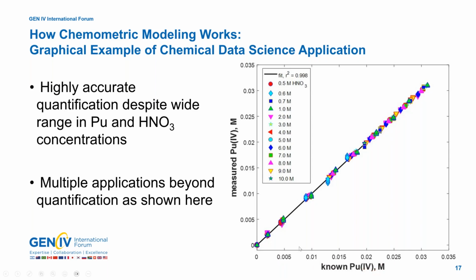And I want to highlight that we're looking at a parity plot where we've got two dimensions of variability. We've got the variability of plutonium-4 concentration, so that impacts the signal strength or intensity of plutonium-4. And we've got variability of nitric acid, so we're really changing that fingerprint of plutonium-4 quite drastically across this range. What we're looking for on this parity plot is a one-to-one correlation between measured and known, and that's the black line here. You can see that despite all of the variability, both concentration and matrix for plutonium-4, our data is lining up beautifully with that one-to-one correlation, indicating high accuracy of measurement.